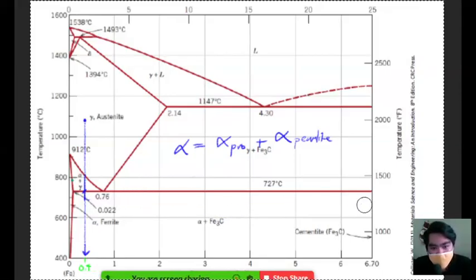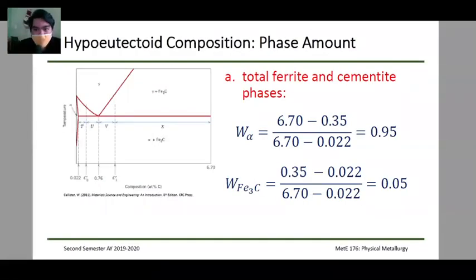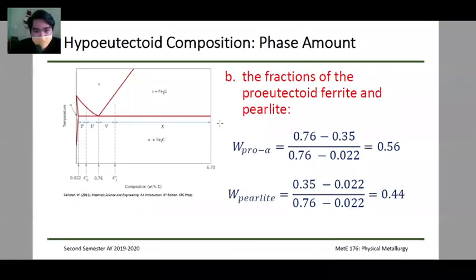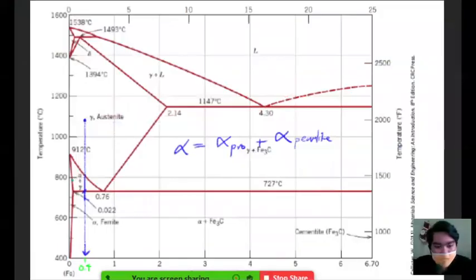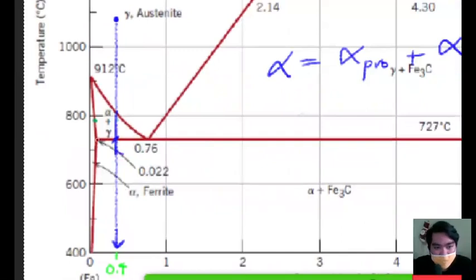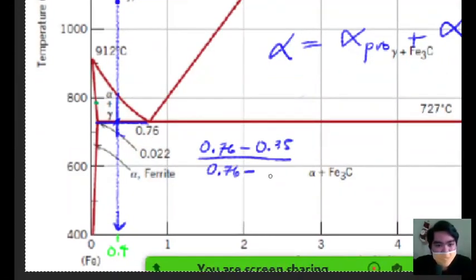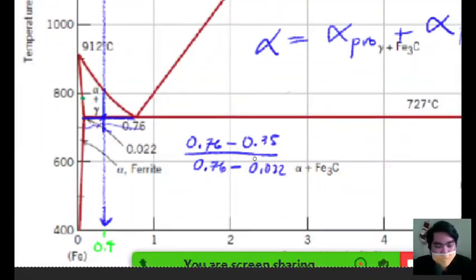If we want to get the pro phase, if we are only computing the pro phase, then we measure only this tie line, from here to here. Okay? So if we measure this tie line from here to here, we get 0.76 minus our composition, which in the example is 0.35, so 0.35 divided by 0.76 minus 0.022, which is the entire length of this tie line. Then this will be your pro-alpha phase. So if that is your pro-alpha phase, then the remaining is the gamma phase.